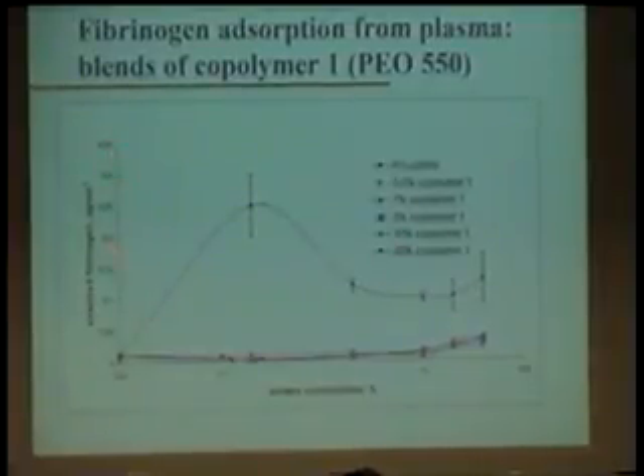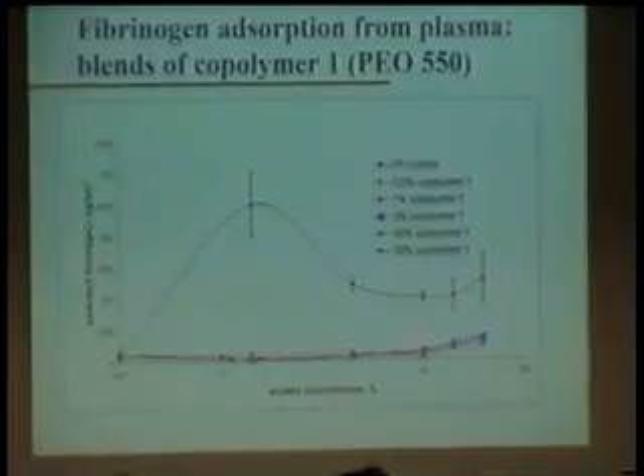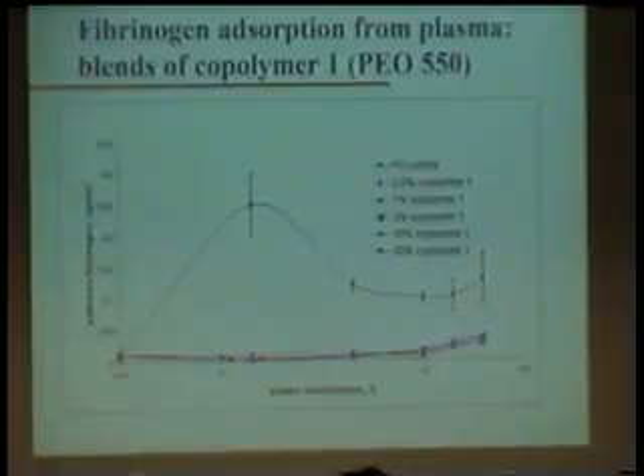So this is again adsorption quantity on the y-axis, and it's percent plasma on the x. What we do here is we take undiluted plasma, 100%, and then we serially dilute it with TBS. And this gives us a kind of equivalent isotherm for our plasma situation. So the main point to notice here is that there's a huge difference between the control and the blended materials, a huge decrease in protein binding in blood plasma. And so this is another demonstration that these things work quite well.